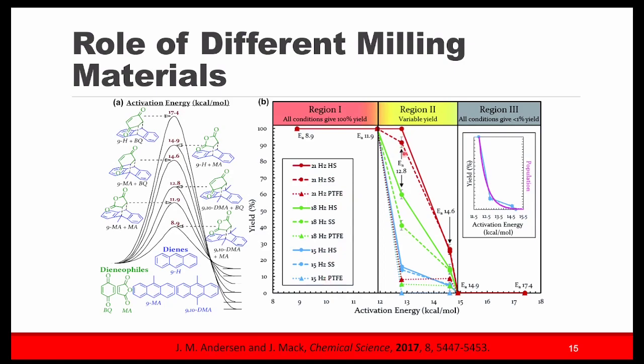And here you can really see that the material that you use has a pretty significant impact on the actual rate of these transformations. The most dramatic here being at 18 hertz, where with hardened steel you're getting 60% conversion, but if you do the reaction in Teflon, you're getting only 5% at this point. So I thought this is a really nice example of showing both the effect of frequency as well as the materials that we talked about that you can use in ball milling, and how that might affect your reaction kinetics. And so in this case, if you need to be running the reaction in Teflon, you'd have to either go longer or somehow impart more energy into the system by increasing the milling frequency or something like that.